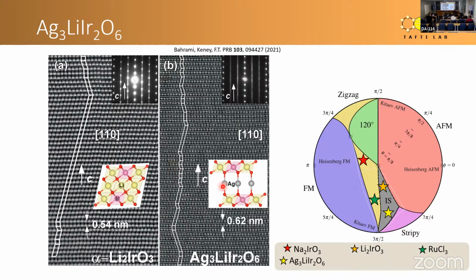And the reason for it is that these silver atoms between the layers form this dumbbell coordination, which is much more fragile, or less robust, than the octahedral coordination of lithium atoms. So the adjacent layers can every now and then twist with respect to each other, and they create this kind of zigzag stacking of the monoclinic unit cells. And that's why silver lithium iridate has more stacking faults.